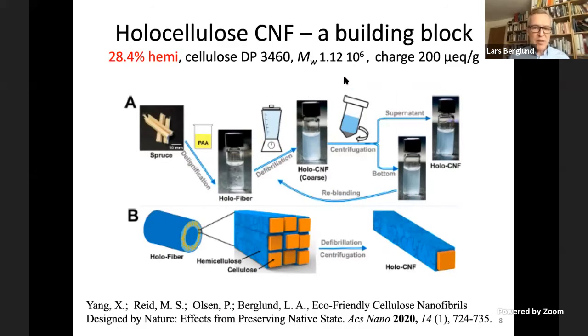This is where we spend a lot of our time at the moment, on holocellulose CNF. So by mild delignification, we managed to preserve a large extent of the hemicellulose. So we have 28% hemicellulose, very high molar mass because we're not degrading the cellulose, and substantial electronegative charge. So by disintegrating in a very simple way, just using a kitchen blender, we can create these very interesting CNF fibrils.